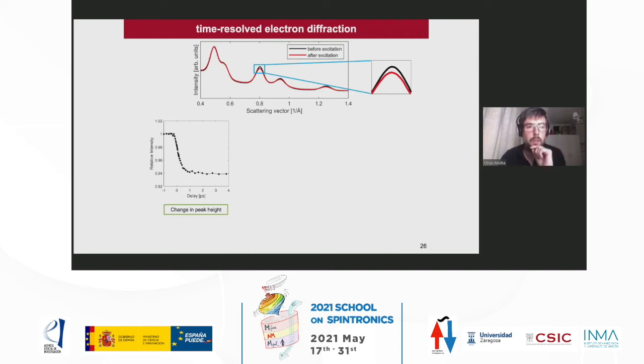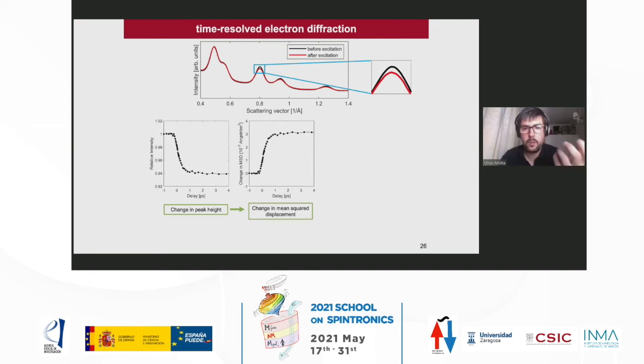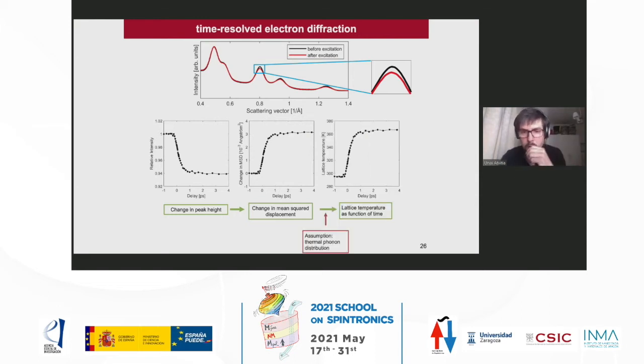As a function of time, we can translate this change into a change in the mean square displacement of the atoms, and by assuming a thermal phonon distribution, obtain the lattice temperature as a function of time.